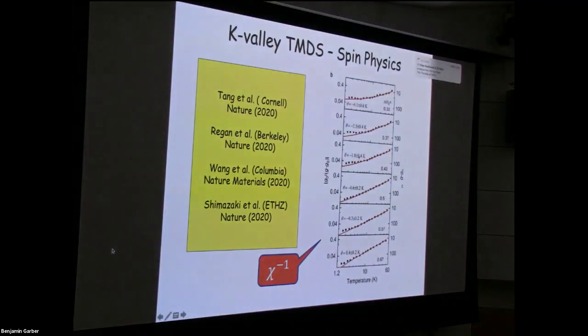What you actually see here, maybe a little bit in this early experiment, is for what was called half-filling. So that's where you expect one electron on every lattice site. And those of you who know Hubbard model physics know that there you expect an insulating state if interactions are strong. And here you can see at half-filling, they're starting to see more or less Curie-Weiss localized electron type response to a magnetic field, whereas at other filling factors, what they see is more metallic-like.